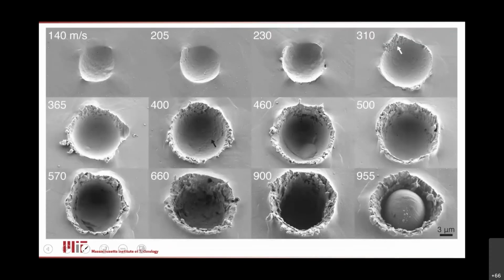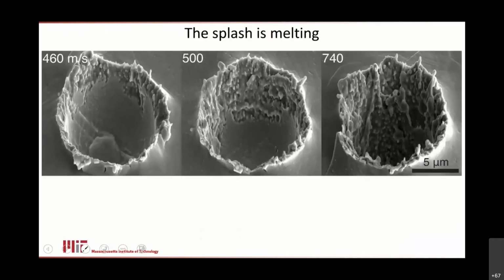So we can go in and we can look at these. We can see things that bounce gently. We can see one particle manage to embed itself, but that's an outlier case. And actually, we can zoom in right where we saw that divergence. In fact, that was at 460. So here's a zoomed in view. And I can tell you now that the splash in this case is not about hydrodynamic plasticity. This time the splash is associated with melting. And it's unequivocal from these micrographs because this is the first speed at which we saw the little splash.